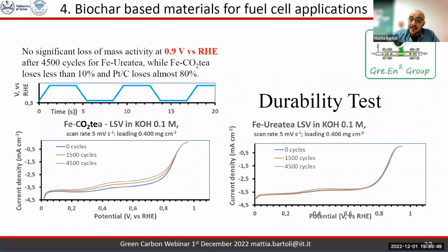Furthermore, the durability test shows that our material, after 4,500 cycles, practically did not lose activity, and platinum carbon materials lost up to 80% of the total activity. Methanol is not a good environment for platinum metals, platinum-similar metals like platinum and palladium. It's a very stressful medium. But the combination with iron and biochar, well, they survive, and they are still working after 4,500 cycles.